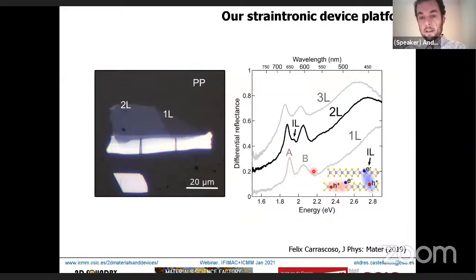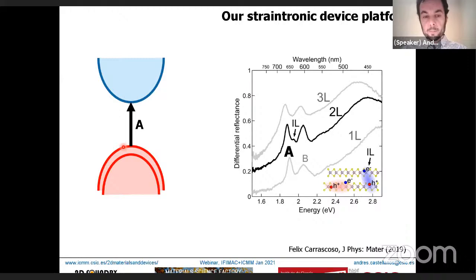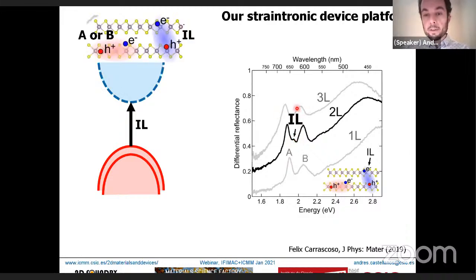In the reflectance spectra of this molybdenum disulfide, you have these peaks corresponding to different exciton resonances. The A peak corresponds to the direct bandgap transition at the K point from the valence band to the conduction band, giving this resonance in the reflectance spectra - already direct information about the bandgap. We also have the B peak, corresponding to another transition because the valence band of molybdenum disulfide is split due to spin-orbit interaction. Interestingly, in multi-layers we also have this little hump labeled IL, the interlayer exciton - another transition where the electron and hole live in different layers, hence the name.